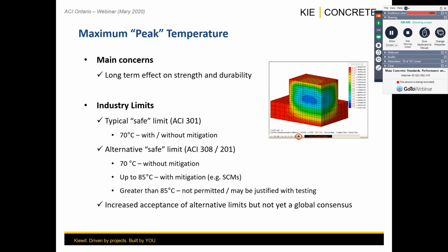That has been found to be above 85 degrees Celsius. The same with durability, but in durability, you have different limits. Above 70 degrees Celsius, without any mitigation, without any improvements in the chemistry, without any SCMs, for lack of a better term, you are likely going to see risk on impacting the durability of the concrete.